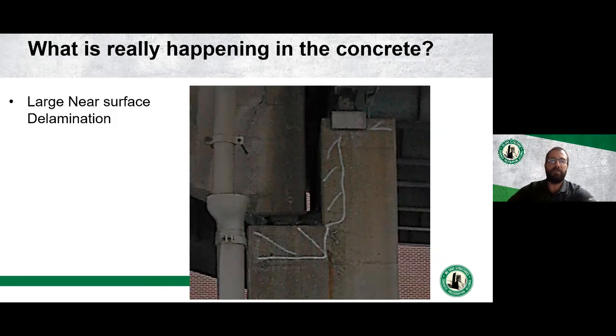So I always like to start off my presentation by talking about what is it that we're really looking at in a concrete structure. And so here on this screen, we have a large near surface delamination. You can see here we've hammer sounded this structure, and the white hatching is where there is a large near surface delamination. Now that is obviously concrete that is debonded. There's corrosion activity there. It's going to cause deterioration and fall off.